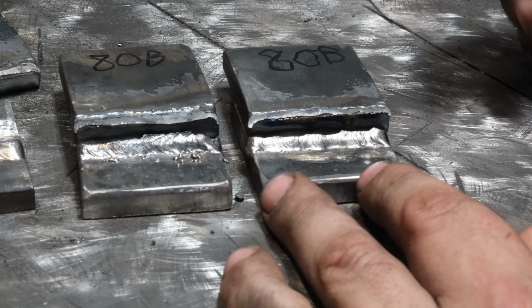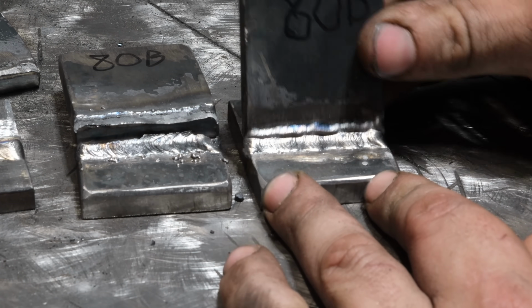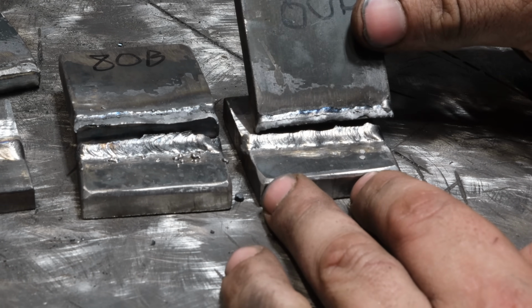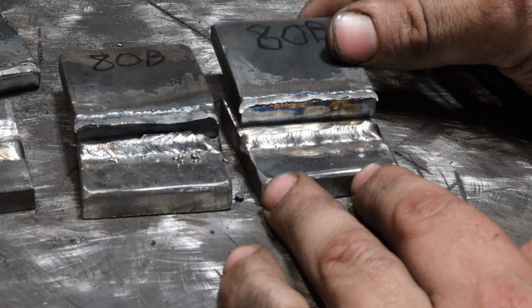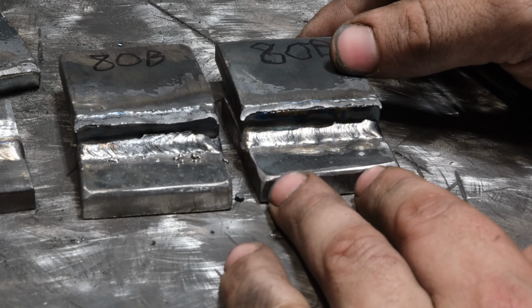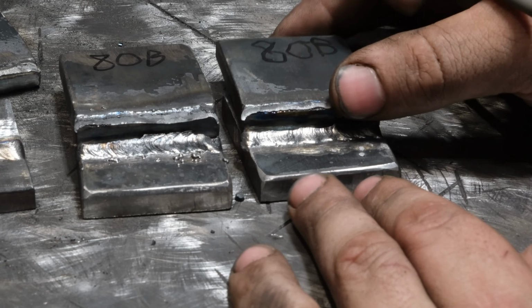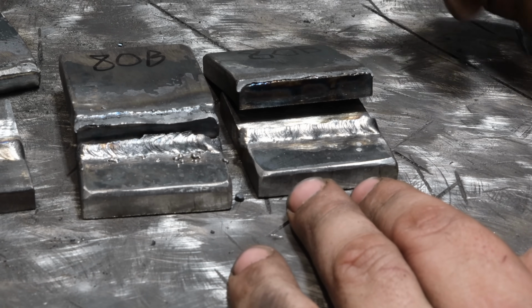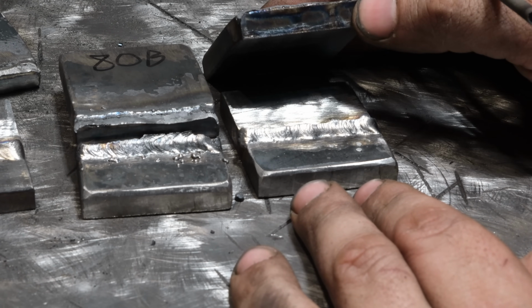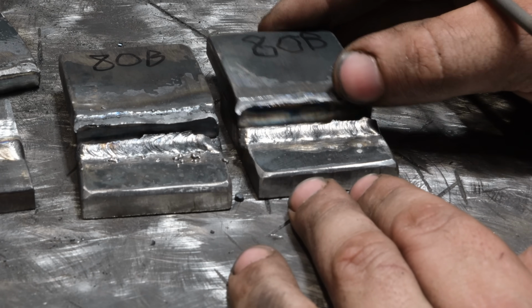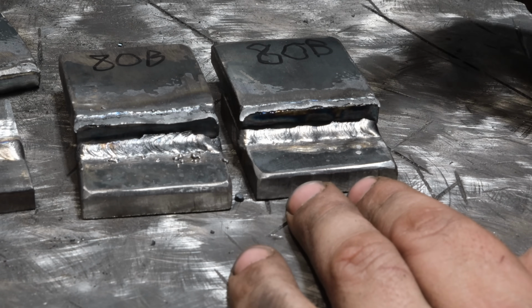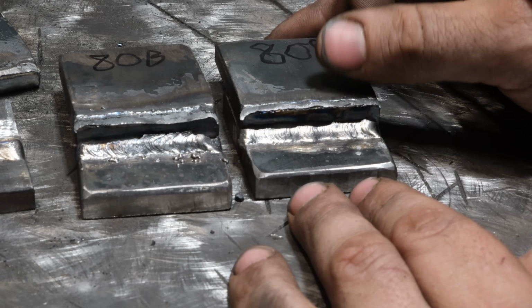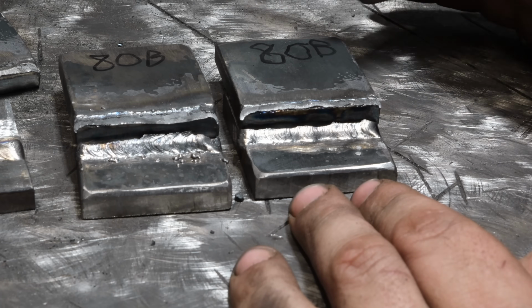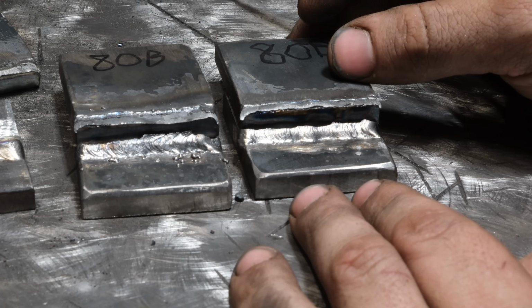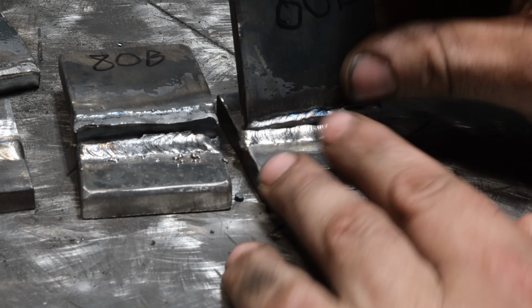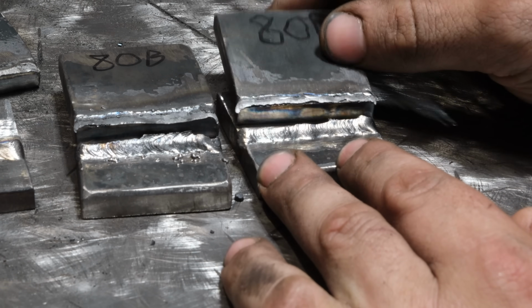The second one that we did that was defect free. That one broke as I would have expected for this particular rod, which is kind of more or less right down the middle. Not all rods will break like that, but this one in particular did. Based on what I see here, well, one thing, penetration is very limited with this blue 80 series rod. The weld itself appears to be fairly strong as far as the pressure it took initially, but once it was pulled, stretched at all, it kind of broke.